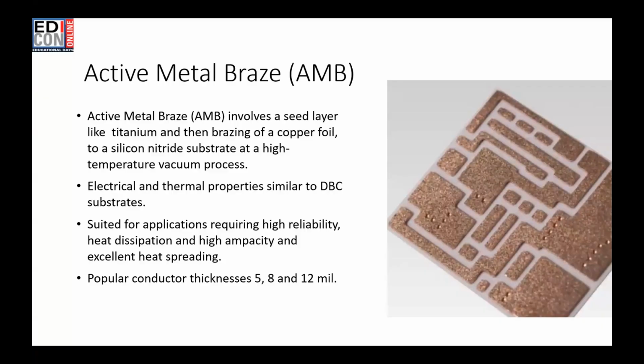The active metal braze involves a seed layer like titanium and then brazing of copper foils on one side or both sides to a silicon nitride substrate. It can also be done on other materials, but silicon nitride is most popular at this time. Electrical and thermal properties are very similar to DBC. These are also suited for high reliability, heat dissipation, and high current requirement applications. The popular thicknesses of the conductors range from 5 mil, 8 mil, and 12 mil.